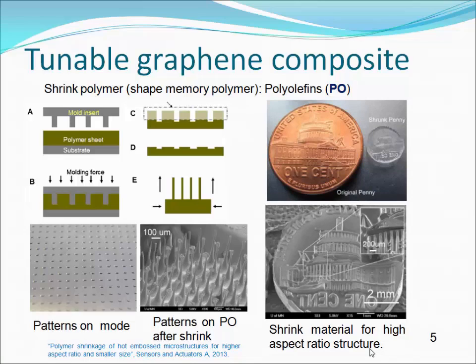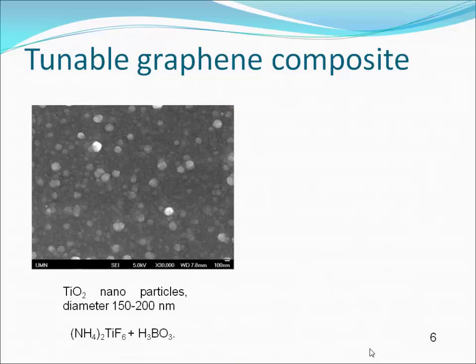After shrinkage, the lateral size of the PO polymer reduced to about 1/3 of its original size. But the depth of the patterns on PO polymer increased to about 6 to 8 times. So PO polymer is very suitable for high aspect ratio nanostructures, according to our observation. The titanium oxide nanoparticles we use are derived from the following chemical reaction. The titanium oxide nanoparticles are about 150 to 200 nanometers in diameter.